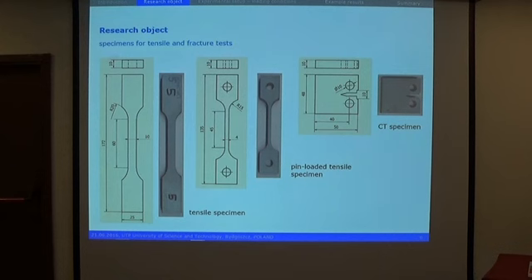For the test, we have used three types of specimen. The first one is a standard tensile specimen. This type of specimen was used for the tensile test with the use of typical hydraulic grips. The second type was the pin-loaded tensile specimen. Such specimens were used when we made tests with the use of a special cryogenic chamber, and the last one was the typical compact tension specimen.